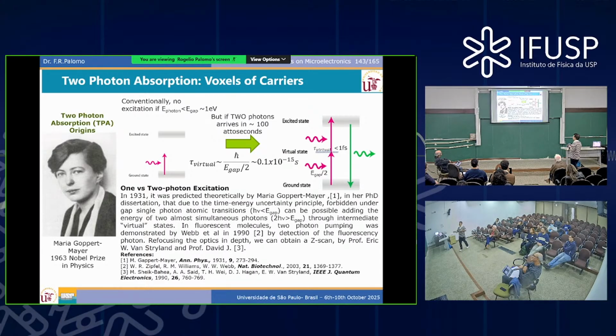You see electrons moving in the semiconductor when those electrons are in the conduction band, in stationary levels. To get those stationary levels, you need basically to double the energy of your photons. Or you can shoot 2 photons in a very short time frame. The second photon has to arrive before 1 femtosecond, because that's the lifetime of that state.